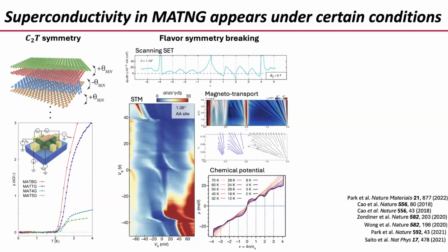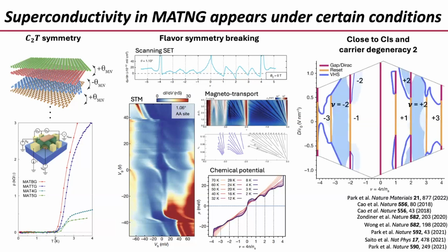It happens in regions where, because we have information about this cascade of phase transitions where the symmetries of the system are broken, okay? In particular, it's stronger in regions where you have 2 electrons or 2 holes per moiré unit cell. 2 electrons, 2 holes plus some additional doping, okay? Plus some extra electrons or plus some extra holes.